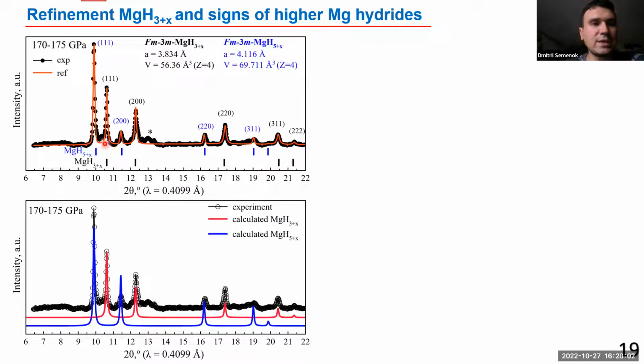Here, I just explained that the diffraction pattern we observed is from two phases, two cubic phases. I showed that by the red line, you can see the first cubic phase, and it perfectly agrees with experimental data. And the second is blue, MgH5+x. You see it also quite nicely describes the observed diffraction pattern.